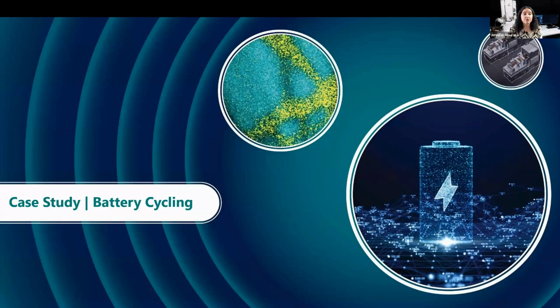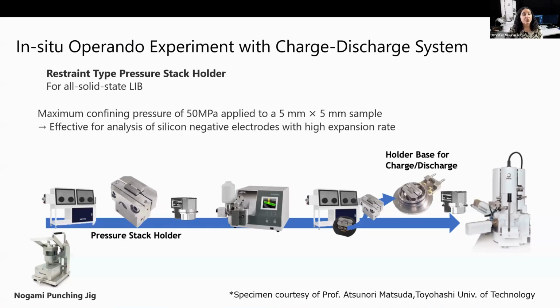And lastly, what I want to do is show an experiment using both the Gather-X and the SXES on JEOL's ultra-high resolution SEM. So this is an example of an in situ operando experiment with a charge-discharge system in the SEM. In order to perform this experiment, we designed a pressure stack holder for an all-solid-state lithium-ion battery. It was designed for analyzing silicon negative electrodes, which typically have high expansion rates.